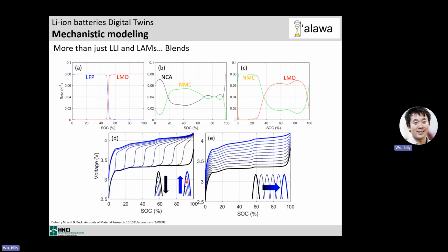For material nerds like me, I really like that one. You probably heard of voltage fade. Voltage fade means that sometimes when the cell cycles, you change the structure. Right now, everything I showed you assumed that your material doesn't change with life. But sadly, some materials do change with life. But we can also handle that with a blend. We just start with one phase at 100%, and with cycling, we have more and more of the other phase. That way we can simulate a transition from one phase to the other.